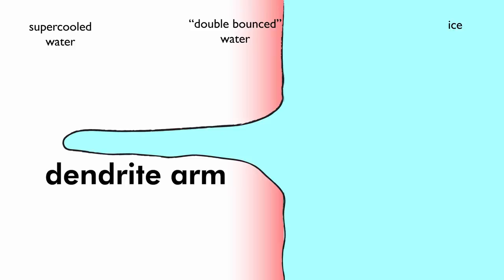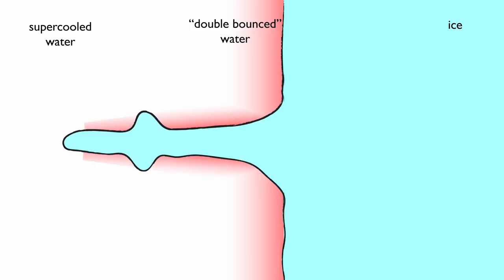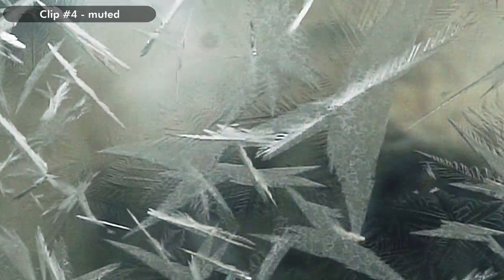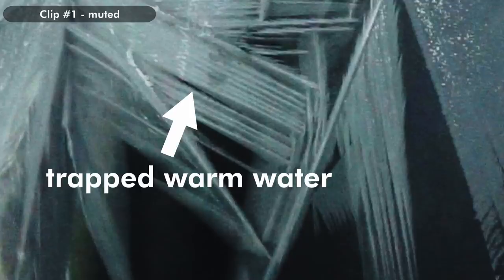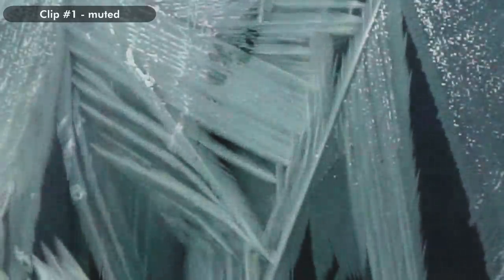That bump reaches even further away from the surface into even colder water, where it grows even faster. This self-sustaining process is dendritic growth, and this spike of ice is a dendrite — it grows outwards extremely rapidly. Once your dendrite gets really big, maybe it gets bumps on its sides, and then those bumps start growing outwards by the same mechanism, making another set of dendrites. It's very fractal. You can even get dendrites that sink into the supercooled water — they go everywhere. The trick is that while you grow your crystal extremely quickly through this dendritic growth process, you end up with little pockets of warm water between all the dendrite arms. I believe the clicking noises you hear during this process are actually formed when adjacent dendrites run into each other, trap little pockets of warm water, and crack.